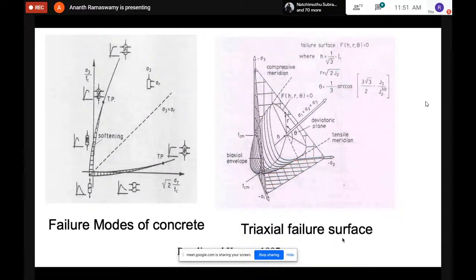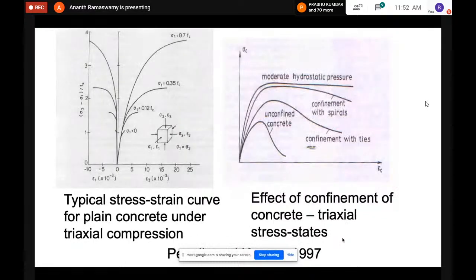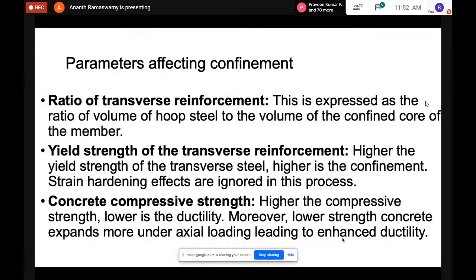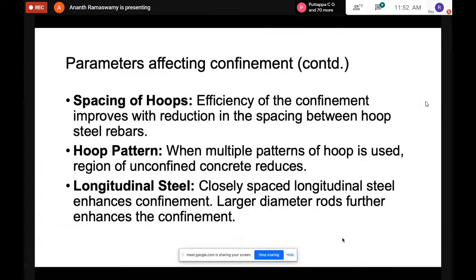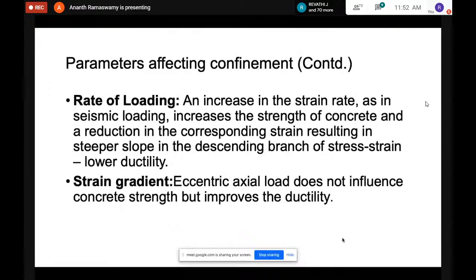You can see, of course, on the right side that with triaxial compression, the failure surface expands in space. That means I am creating a much larger failure surface and delaying failure by having better confinement. And you can see also changes in stress strain response with increased confinement, how things change. So parameters affecting confinement are ratio of transverse steel, yield strength, concrete compressive strength, spacing of hoops, hoop pattern, longitudinal steel, rate of loading, strain gradients.